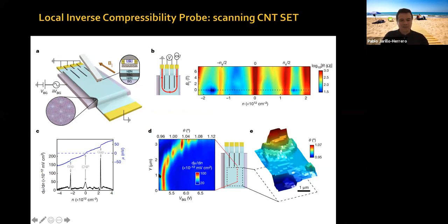And you can see that in this device, over 1 micron, it is pretty uniform at this twist angle, which is actually a little bit towards the smaller range. But then you see these twist angles in different regions and different traces, okay? This is a 3D map of this. Again, this device is a little bit more disordered than we would have liked.